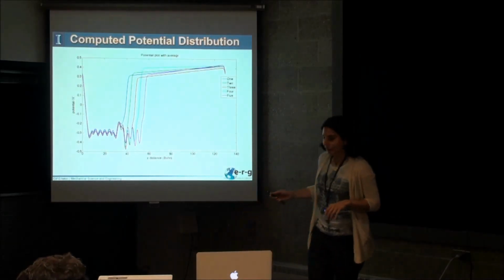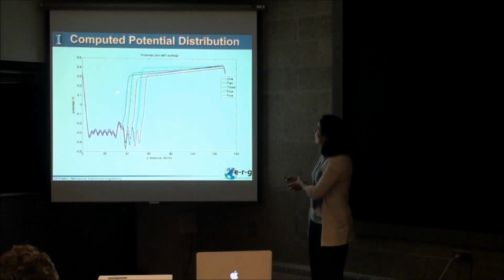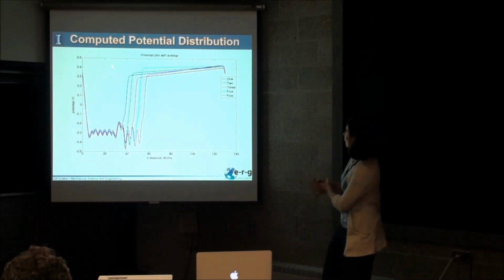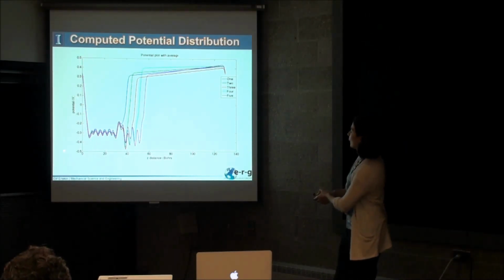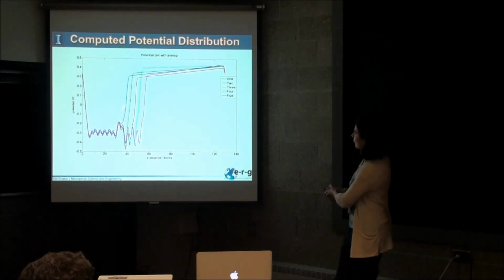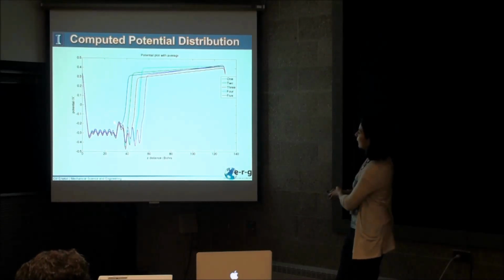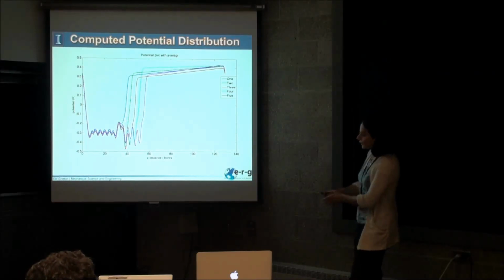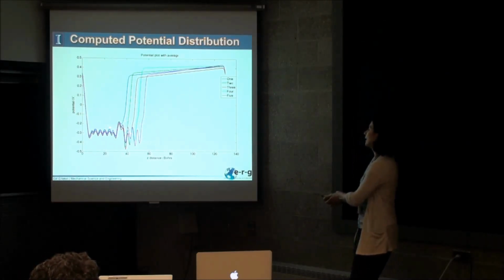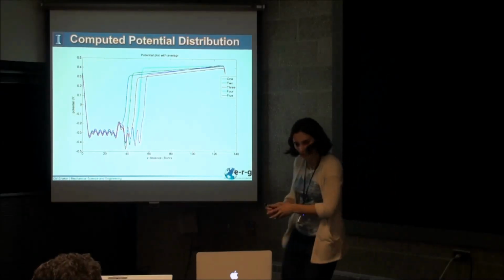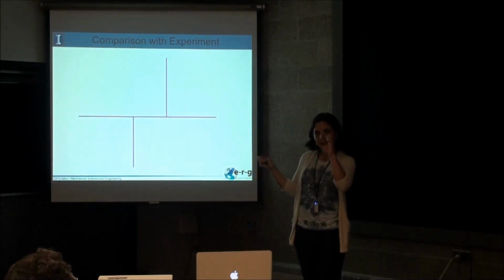Here are some of Rajiv's results actually illustrating that potential divergence. Let me just show what's going on here. Y-axis is the potential. Z-axis is the position. This regime here is the cuprous oxide. And now he's showing what the potential looks like for different numbers of layers of TiO2 on the system. And you can see that as the number of layers of TiO2 increases, that potential drop is kicking in. We see it kicking in, but what we do see is that, at least at that particular size scale, those systems appear to be stable.